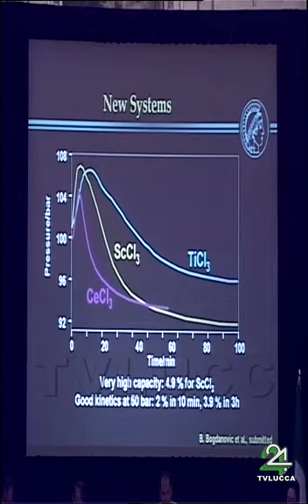The other important thing, I think that's the field where we still have the most deficiencies, is low pressure rehydrogenation. Normally we do our rehydrogenation, as you see here, at a pressure of around 100 bars. This is not optimum because at 100 bars you typically have a cylindrical tank, which is difficult to pack in a car, and so you want to have 50 bars or even lower.